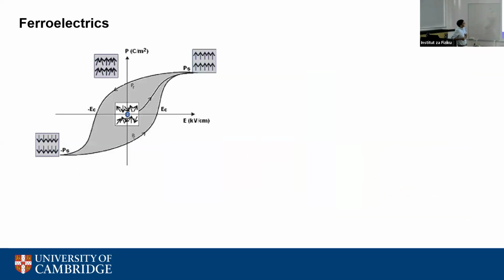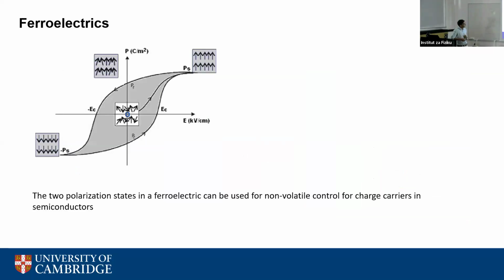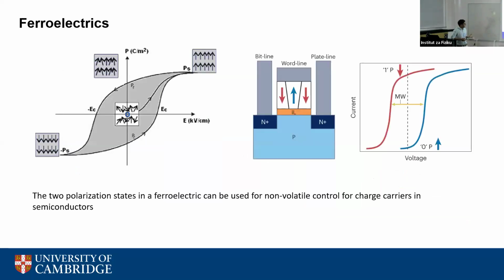Sorry for this pixelated image here, but this is a classic ferroelectric. I mean, you might be familiar with what a ferroelectric is. A ferroelectric is a material which can have a bistable state due to two electrically switchable stable polarization states. And these two states can be used for non-volatile control of charges in a semiconductor. And people have shown that if you replace the dielectric in a gate with a ferroelectric, you can achieve a memory, because now you mimic the hysteresis of the ferroelectric in the charge transport, and you can store information along with processing information. So it's like a logic plus memory device.